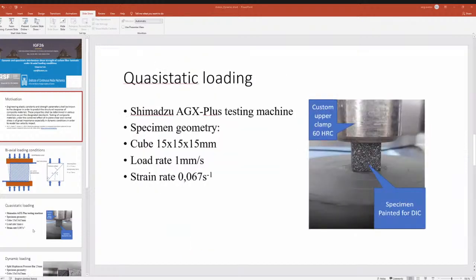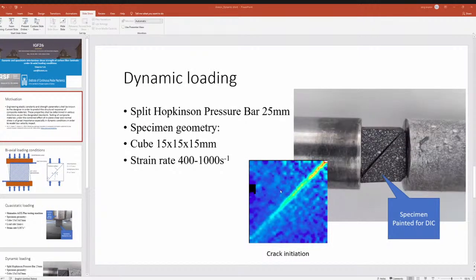And we have done two types of tests: quasi-static on Shimadzu AGX plus testing machine. As you see, specimen is coated for DIC tests, and also dynamic tests using split Hopkinson pressure bar. In this test, we also did high-speed filming, and you can see, for example, early stage of crack initiation. So crack was initiated at upper right corner and propagates downwards.